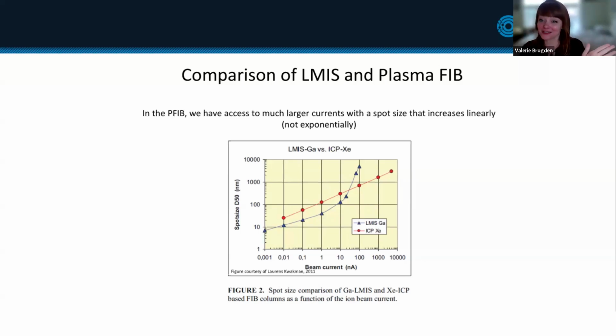And sometimes that works really well. I find that it works really well on geological samples. Sometimes it does not work really well. You know, just like Prahlav said, FIB is really a dark art. So it's all about just trying things until something works. But I will add probably the most obvious thing you can do is step down your current a lot. Once you approach the final polishing, you need to be doing that with a very low beam current.